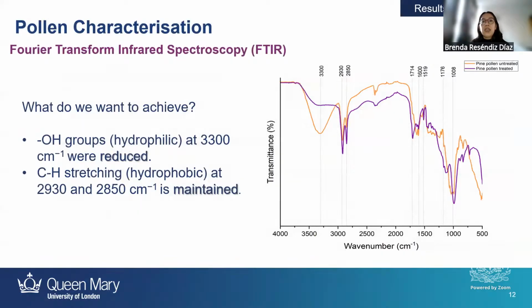So that's why I use FTIR, Fourier transform infrared spectroscopy, to know the chemical groups present in my samples. So what we want to achieve is actually to reduce the OH groups or hydrophilic groups present on the sample. We can observe these at 3,300. So they actually reduce from the untreated to the treated.